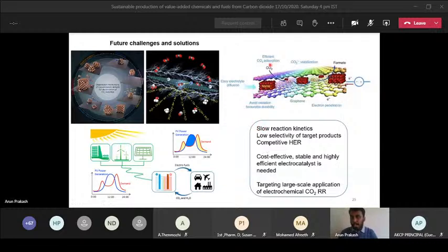And efficient CO2 adsorption matters. If you have a porous catalyst, you have to avoid oxidation and consider durability. As I told you, you can have a core shell structure like polypyrrole coating, and you can increase the stability. Electrolyte diffusion, different kinds of material, selectivity and electron penetration all matter.